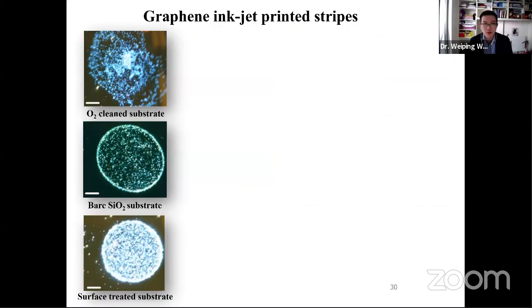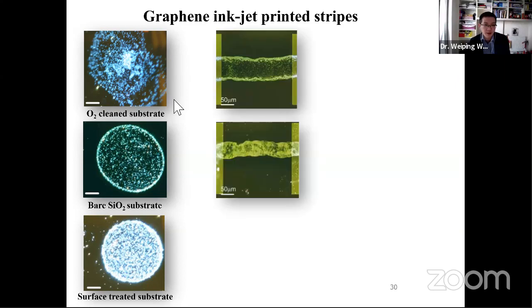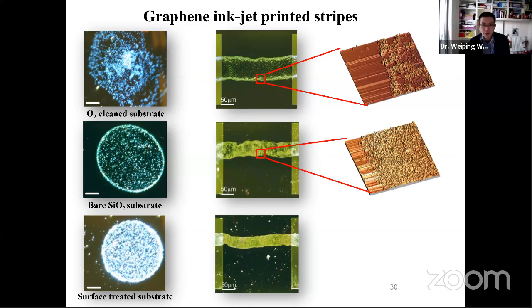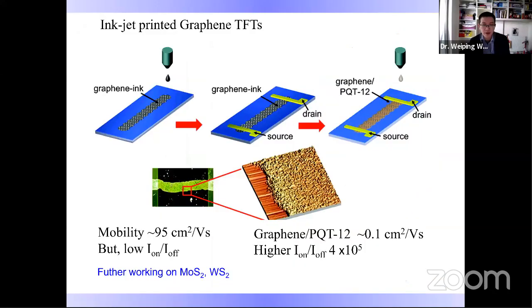bendable substrates. During this fabrication, we found that this type of graphene, due to its hydrophilic nature, is difficult to directly inkjet on the substrate. Rather, the substrate needs to be treated with a kind of silane and so on. After a range of comparison studies, we found the optimal condition, and we successfully inkjet printed graphene as well as graphene covered with the conjugated polymer polythiophene, which is PQT12.